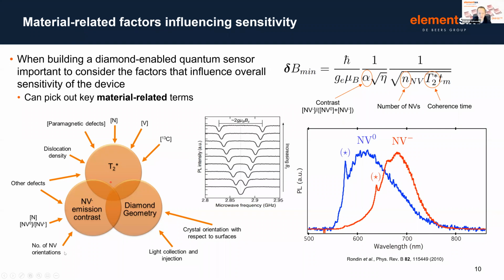So in practice, what this means when we produce a diamond sample for this sort of application is that we need to concern ourselves with a whole host of material-related factors, such as the things that can fundamentally affect the coherence time, T2 star, which are things like the nitrogen that we've added into the material, and the amount of other paramagnetic defects that can exist in that material. And we also have fundamental things like the size and shape of the diamond sample, which can influence how easy it is for us to inject the light into the diamond sample and then conversely collect the luminescence that we're interested in.